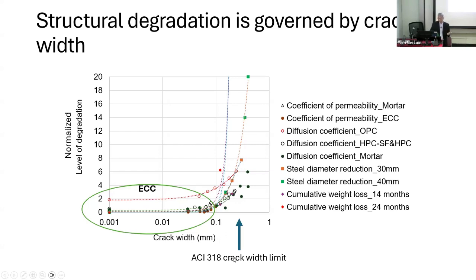And what is interesting here is I also put this mark here, this blue arrow here. That's the old ACI, American Concrete Institute, the building standards. And there was an old limit here, which no longer is present now in the new code. But it used to be there, and I'll explain why that changed in a moment. But here, what is interesting is that if you design your structure and make use of steel reinforcement, typically that's what you do, and try to keep your crack width to below this level, then if you are successful, it should be relatively low, although it's starting to go up even in this range, right?